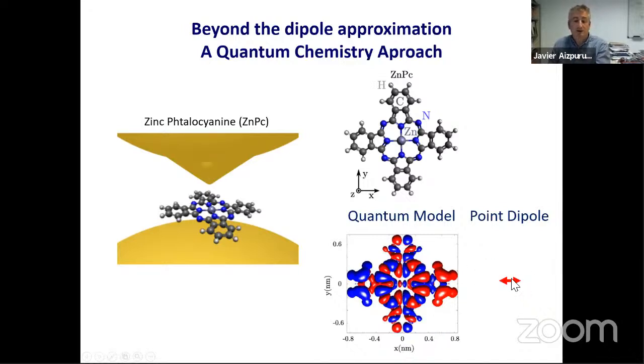Here I put this point arrow with the point dipole, and this is what the dipole of the molecule really looks like. This is the transition electron density of this zinc phthalocyanine center, right? And we put it here in the pico cavity. This is what I was telling Luis Martin Moreno before. If I want to describe the resolution in these cavities, it's enough that to the standard nano cavity, I add this pico bump and it reproduces the localization of a few atoms at the atomic scale.